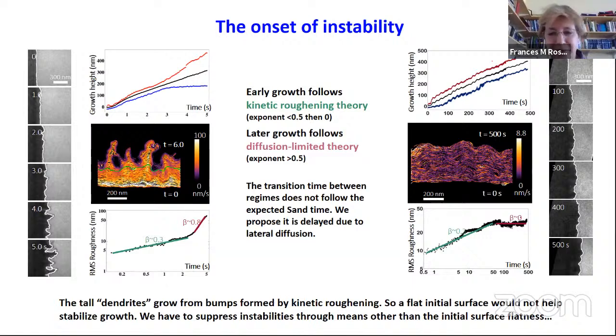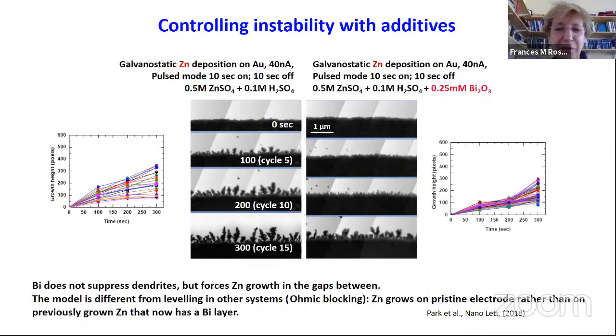But maybe the most universal thing here is that these tall instabilities grew from small bumps formed by kinetic roughening. So however much you polish the electrode surface, it's not really going to help. The surface intrinsically will become rough, and then intrinsically will form dendrites. So we have to suppress instabilities through means other than the initial surface flatness. And one of them, a well-known way, is to use additives.